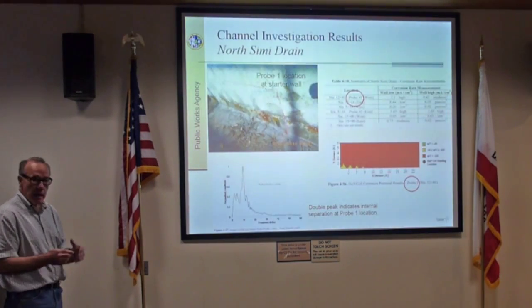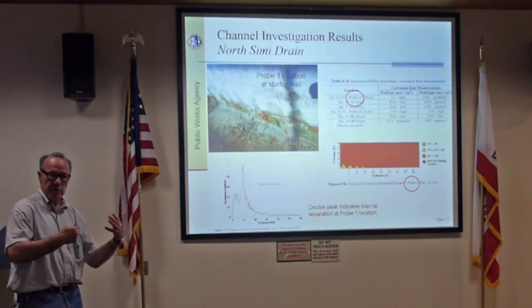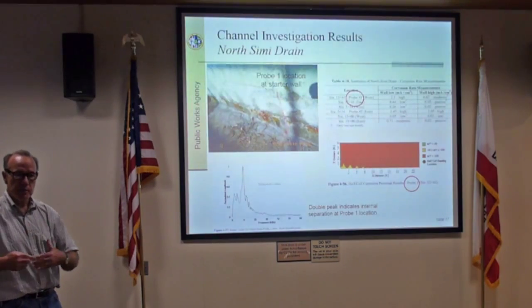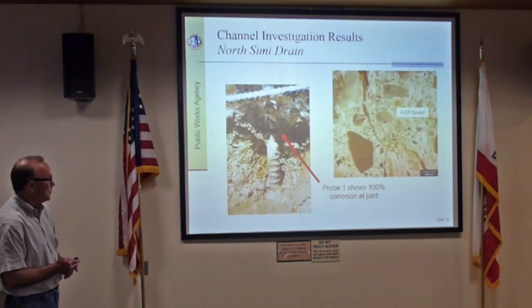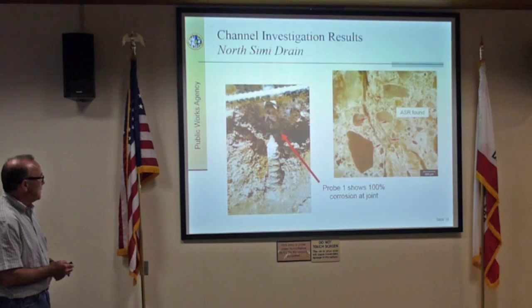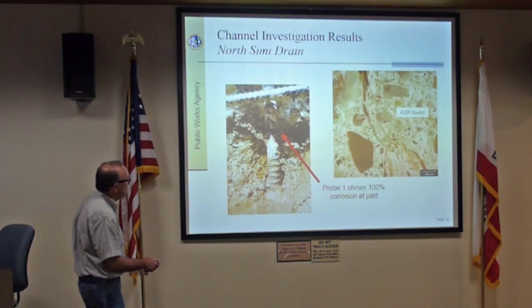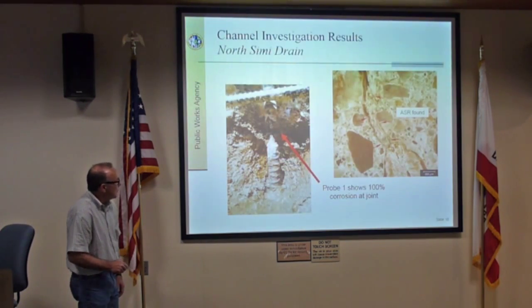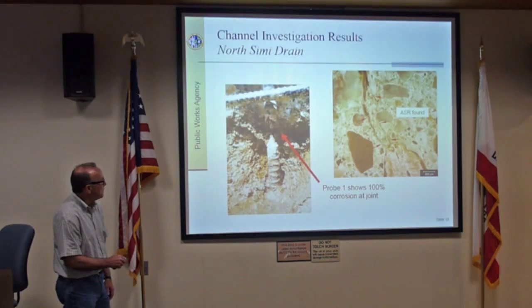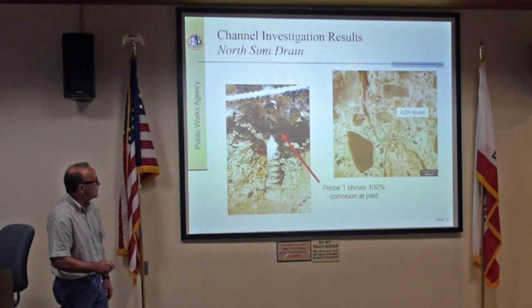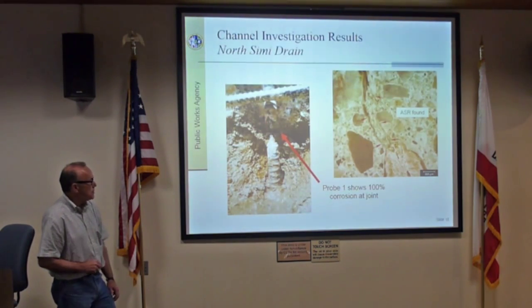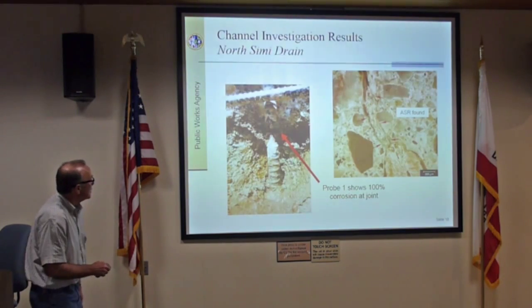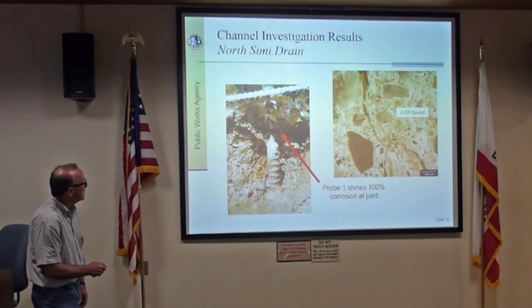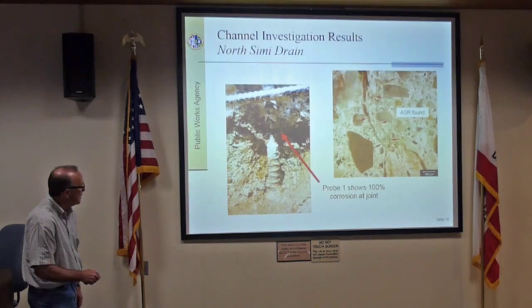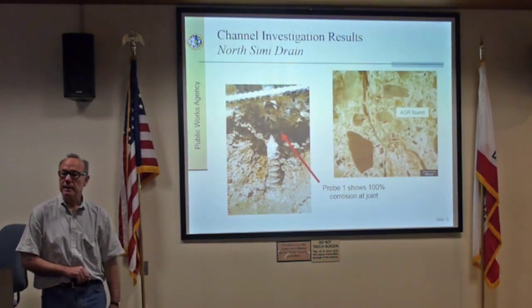So, you build a picture. You do these various tests, and you can build a picture of what seems to be more vulnerable to all this. This is the problematic one here, right? So we have this bar, and all of the steel from that probe shows 100% corrosion at that joint. And you look at this rebar here, and the rest of this rebar here, and there's hardly anything occurring.